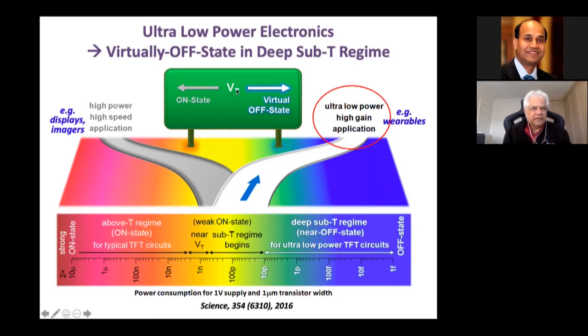When you talk about a low power sensory interface, you can take a look at the transistor and ask where it is sitting in terms of its operation mode. If you go right, that's the virtually off state. In other words, if you look at the currents in a transistor, you get smaller and smaller values, so the transistor is approaching the off state. But if you went to the left, as you see here, this is what we call the above threshold regime, where the transistor is in the fully on state. This is the state used for digital logic and also for high amplification, simply because you have a current that's independent of voltage. So this is the regime of using it as a stable current source.